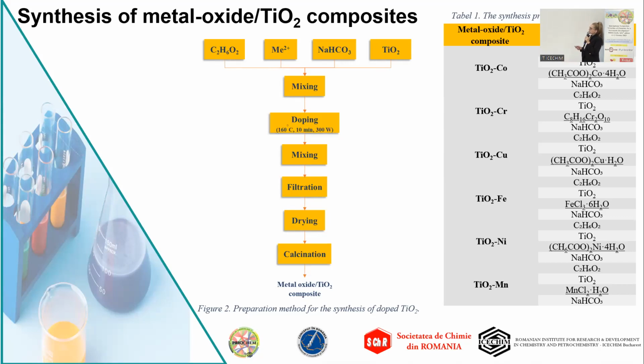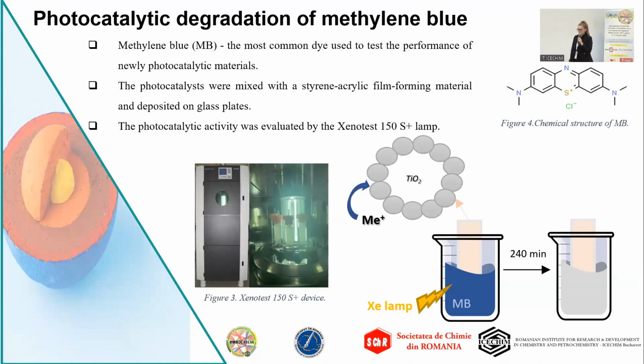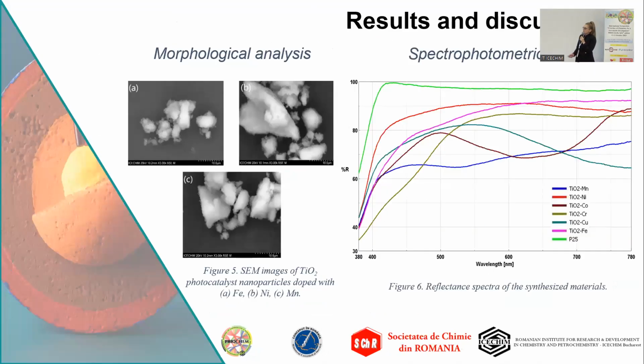In order to determine which metal ion is more effective, 6 samples were prepared, as shown in Table 1. As an application, we have chosen to present the photocatalytic degradation of methylene blue from aqueous effluents. Methylene blue is one of the most widely used industrial dyes. For this purpose, the synthetic photocatalysts were mixed with a styrene acrylic film forming material and deposited on glass plates. The photocatalytic activity was evaluated by xenotest lamp.